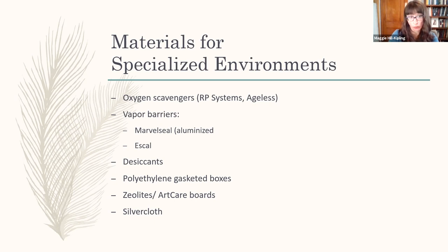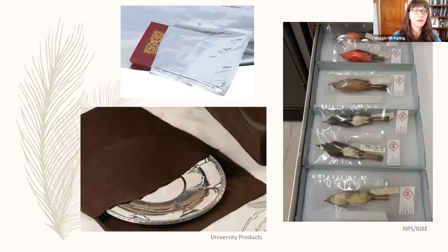And then there's those art care boards that I discussed before and the zeolites. Those are really great for enclosing things, whether it's framed prints or other materials. You may have materials that have a lot of smell to them, even if they've been in a fire. Zeolites are really good at absorbing that odor. And then there's silver cloth, or there's also corrosion intercept, both used to help to preserve metals, particularly for the corrosion intercept, you might use it for copper alloys, and the silver cloth used for silver. Those both have sacrificial metals embedded in the material that corrode before the pollutants will reach the object that you're protecting. And these are some examples of all of those.